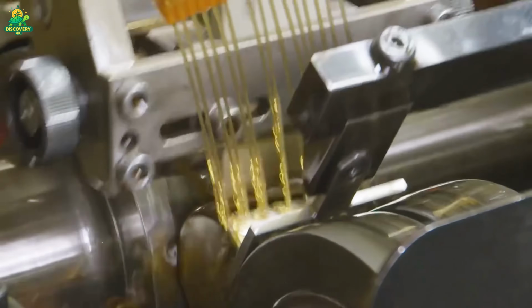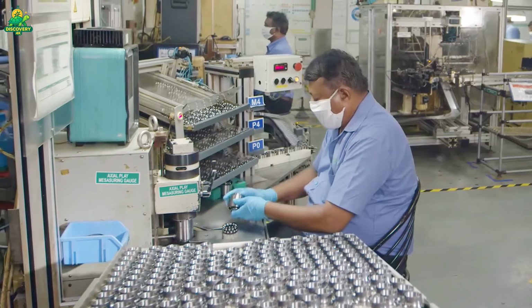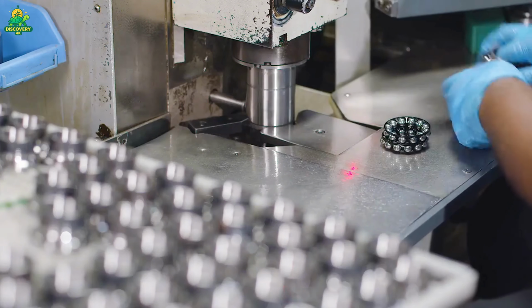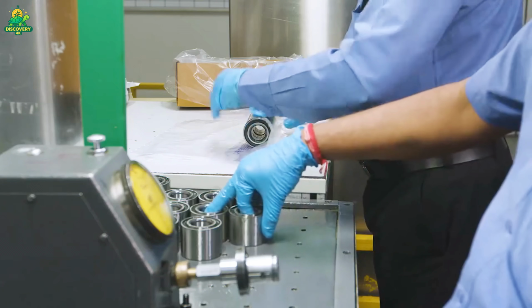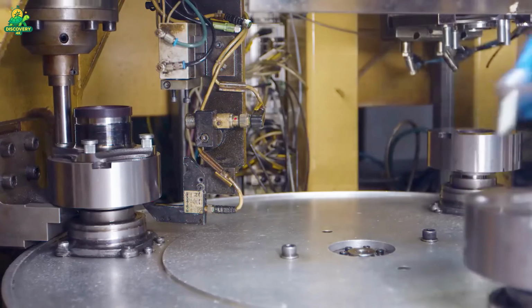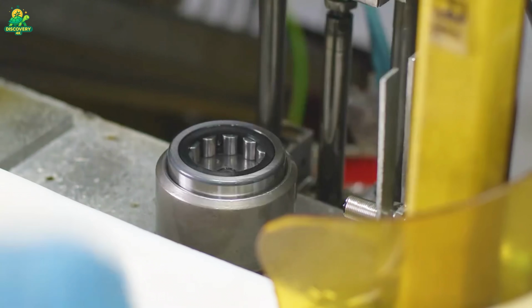Rings are heated again to about 850 degrees Celsius, 1562 degrees Fahrenheit, and then rapidly cooled in oil baths. This sudden temperature drop transforms the steel's structure into martensite, giving it extreme hardness and wear resistance.